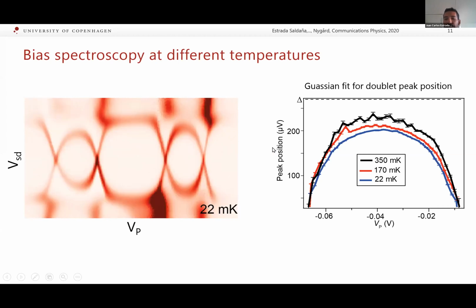And we can fit the peak position of this positive bias YSR loop, the right one here. And we find that the peak position fitted with this Gaussian fit versus the plunger gate voltage moves towards the gap. It's akin to pulling the string of a guitar towards the gap. The notes remain fixed in energy.